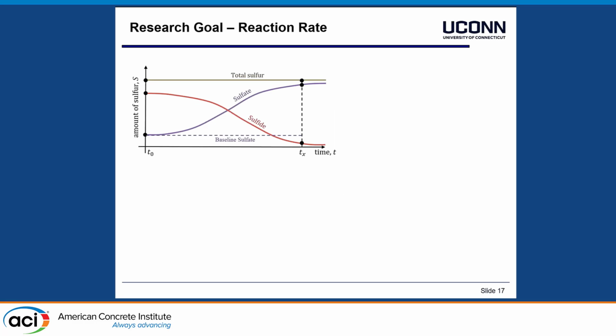And in terms of the reaction rate, if you want to illustrate this, and if we test for the amount of total sulfur in concrete, we then would test and we have this line. But we know we have a baseline coming from the cement in the concrete. We do have a potential amount of sulfide, right, from the pyrrhotite-bearing aggregate, and we have sulfates. Before I say how we test in the field, over time the oxidation of pyrrhotite leads to a release of sulfate, as you know. So sulfate increases and the amount of sulfide decreases. Still, the sum would always be the total sulfur. And this depends on alpha as a factor, like how quickly it reacts.